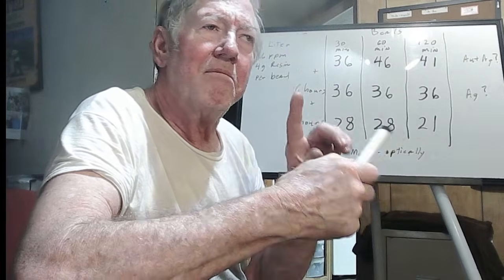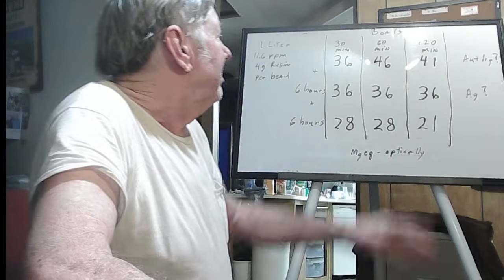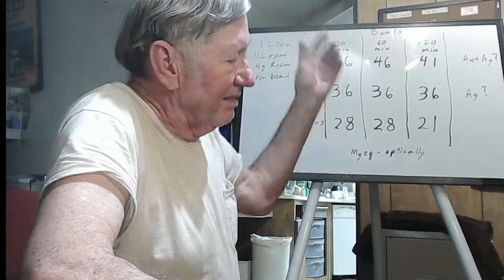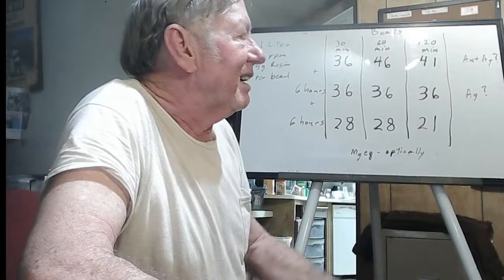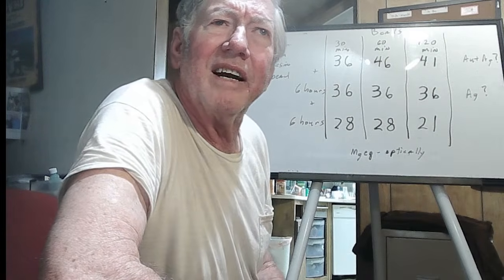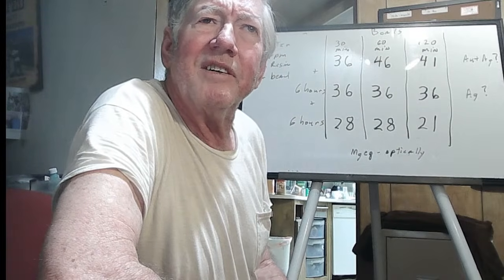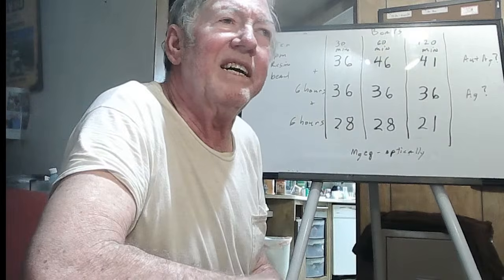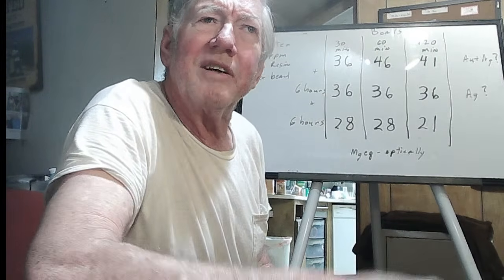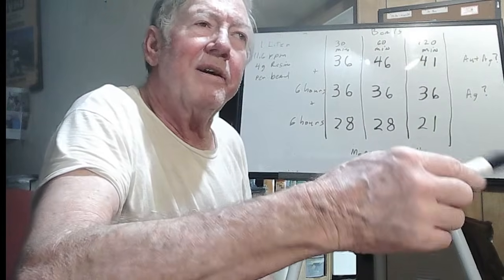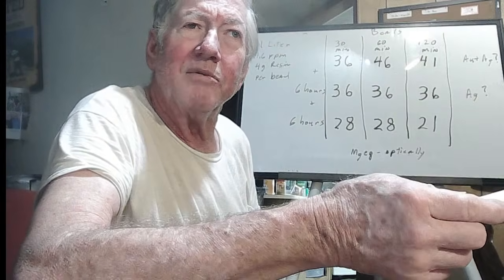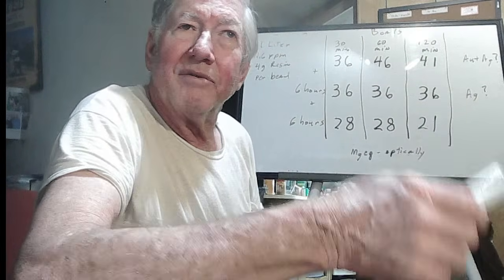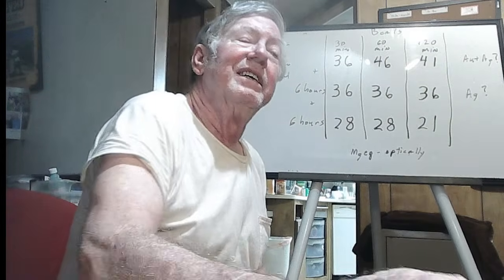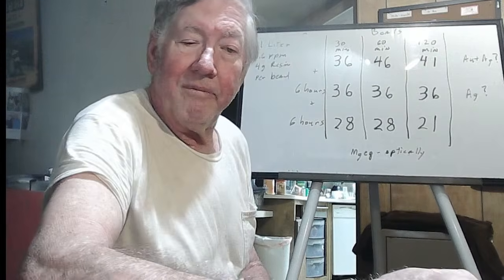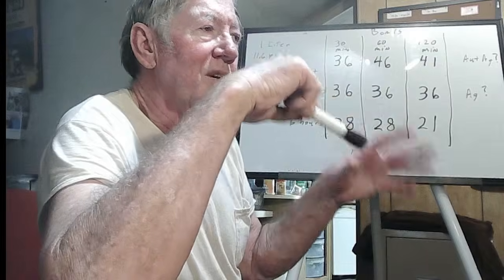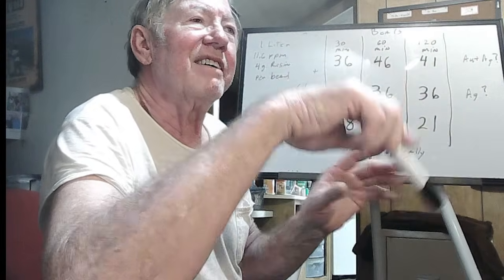And there may be separate batches. You take batch 1 of resin, run it for an hour, dump it out, screen it out, put the slurry back in the cement mixer, throw another batch of resin in it. This particular resin we're using operates in the solution at a pH of about 11 or 12. That's where it's absorbing gold. To strip it, we put it in a thiourea solution at a pH of 1 and a temperature of about 140 degrees Fahrenheit, 60 degrees centigrade, for all you people on the other side of the planet. But anyhow, it's one of those things that I'm trying to figure out how to keep from losing gold.